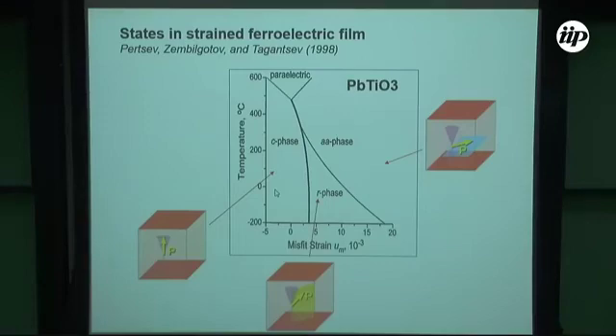So for polarization, we lose this cubic symmetry. This is a classical work, very good work of Pertsev, Zembilgotov, and Tagantsev, done in 98, also before all this boom in ferroelectrics. They considered the phase diagram of the system, and if you have the internal misfit strain introduced by the substrate, you can have loss of the symmetry, so we can have so-called C polarization, which is just uniaxial type of polarization, or we have fourfold degeneracy in plane, which is called the AA phase, or sometimes we can have the direction of polarization along the diagonal. I am using it because this is the most classical example in the physics of ferroelectrics, the new era of ferroelectric films under strain.